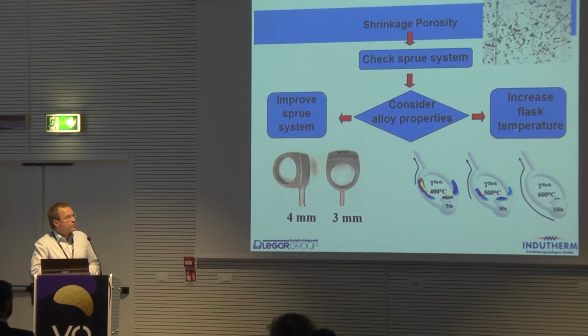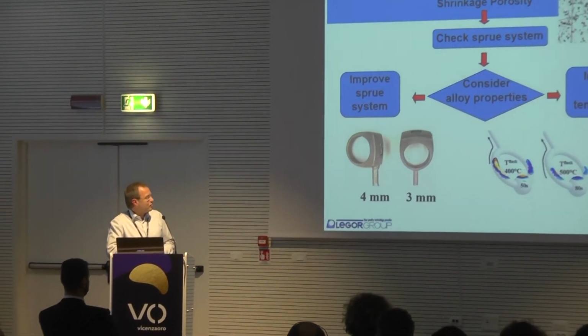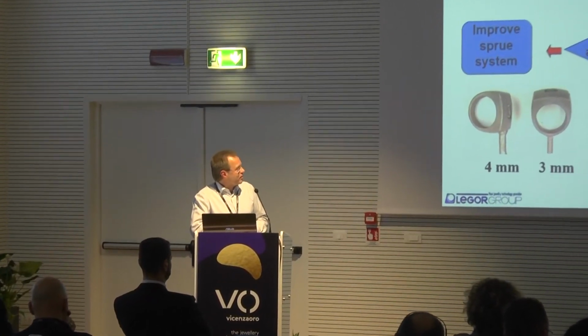Another option can be to increase flask temperature. This is again a result from computer simulation, where we are asking the program to simulate the porosity in the casting. You can see, again, a test item here with a heavy section and the feed sprue attached opposite to the heavy section. You can see that at a low flask temperature, the simulation, and the reality will confirm that, reveals shrinkage porosity on typical locations. And if we increase flask temperature, the situation will improve. This is the other way to approach the problem, but you have to be very careful because higher process temperatures are not always the right solution, as we will see in the next minutes.